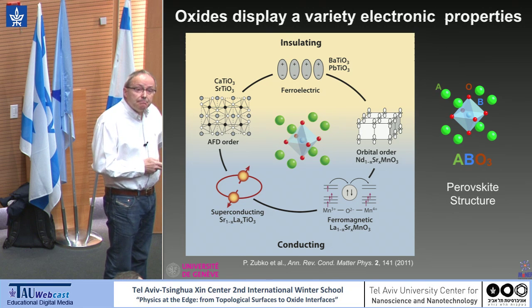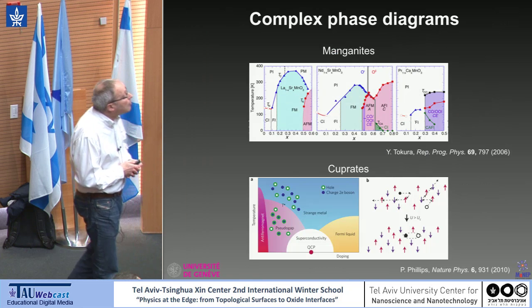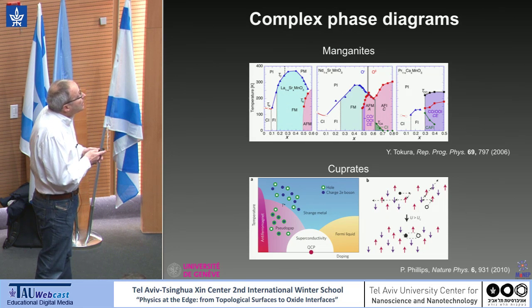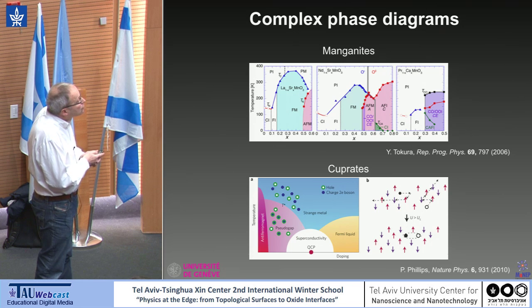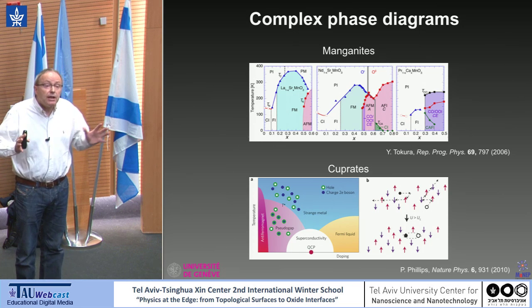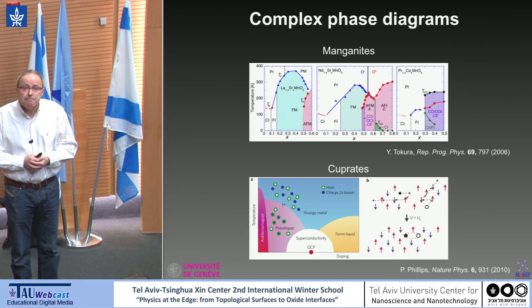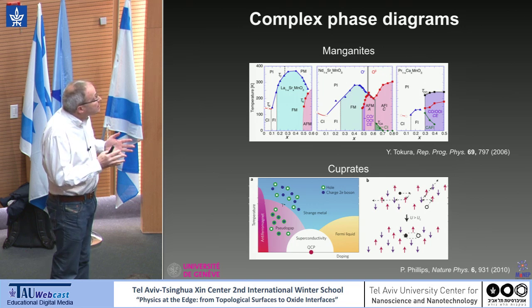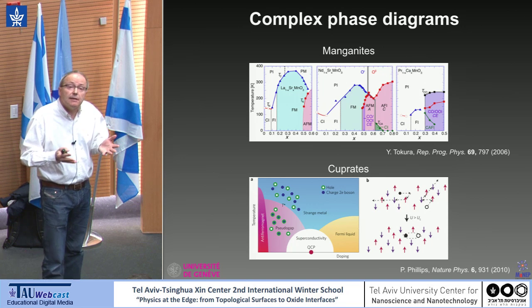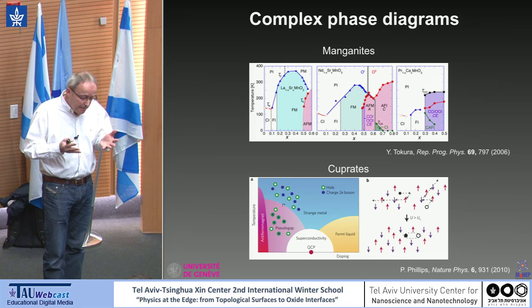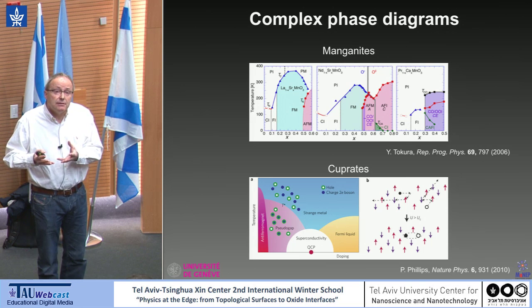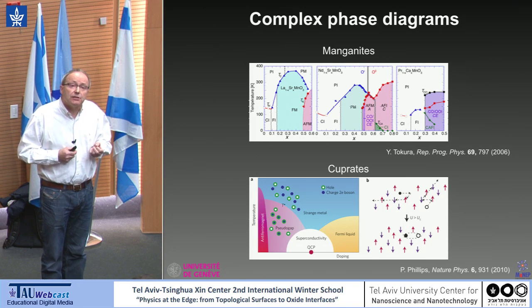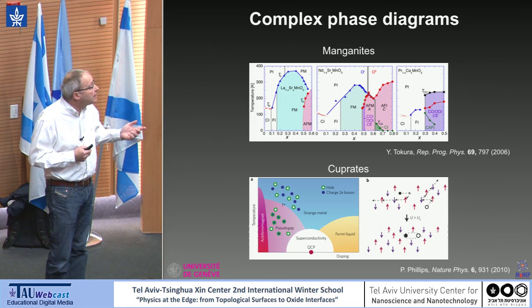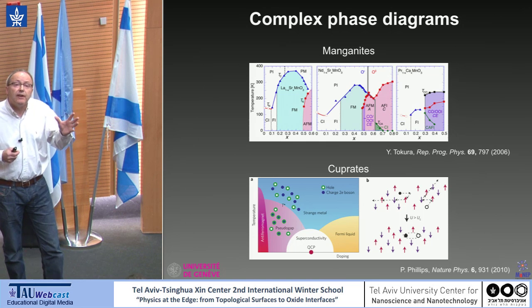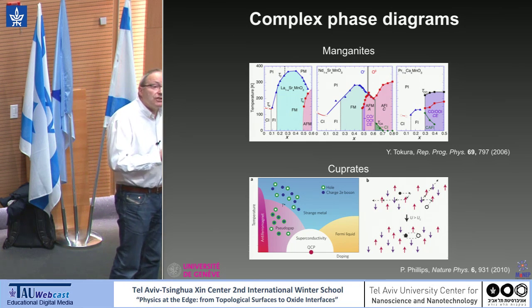We also know that many perovskites display strong correlations and complex phase diagrams. I'm just flashing here two examples. This is a phase diagram of manganites, temperature versus doping, and of cuprates. The only thing I want to show is that when you look at these phase diagrams, you see very many phases. And these phases are telling us that you have different states in these systems which are probably very close in energy. In some sense, a system has difficulties to choose its ground state. And this is why these materials are very sensitive to external parameters like pressure or magnetic field. And sometimes it's enough to modify slightly the environment to allow for a phase change.